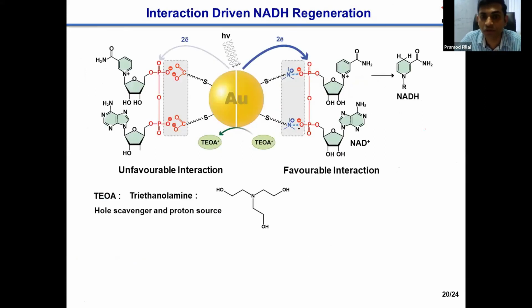So just to remind you, what is our hypothesis? Our hypothesis is based on the electrostatic attraction. So in the case of NAD+, there are 2 phosphate groups which are negatively charged. So we thought of exploring this electrostatic attraction. So we functionalize our nanoparticle with oppositely charged ligands, so that there can be a strong electrostatic attraction between this reactant and the catalyst. In that way, we will be introducing favorable interaction.